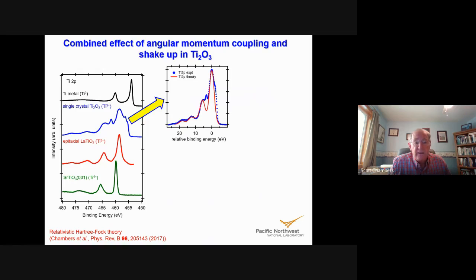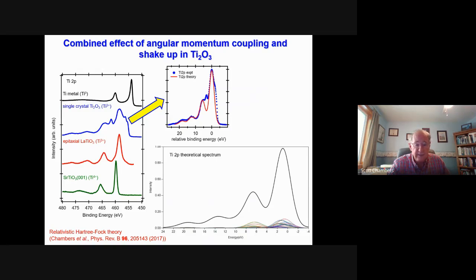As you can see, there are basically 6 peaks in the shakeup spectrum, and his calculations got 4 of them really well. If we zoom in on that calculation, the black is the net spectrum, and below that you see all the little colored curves. Those are all the individual final states that had some intensity in his calculations. There are 320 of them. 213 happen at the higher binding energy end, and most of those are shakeup-type phenomena. Each of them is extremely weak, but when you have 213 of them, they add up to give you what you see in black. The other 107 are shown there, and it's the same thing: each one is pretty weak, but when you add them up, you get what's shown in black.